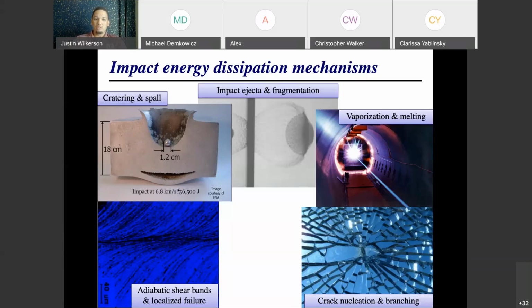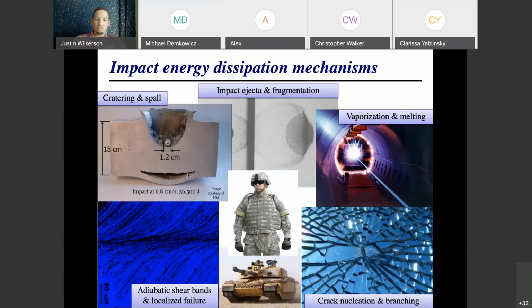So in a typical ductile metal, what will happen is you will nucleate a bunch of voids in this tensile zone. Those voids will grow, they'll coalesce, and they'll form a big crack. And this is a kind of special situation where this spall scab, as we call this piece down here, did not break away. But typically it will break away, and it's actually, unfortunately, the main way that soldiers who are tank operators die in action. And so you could try to double the thickness of this armor plate, and this spall failure can still occur.